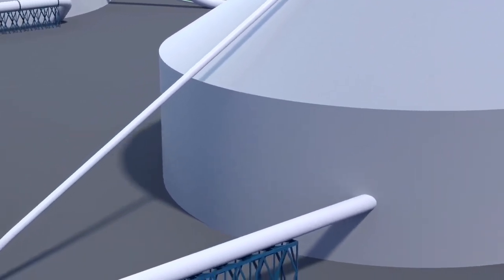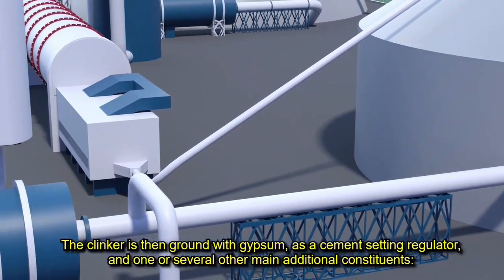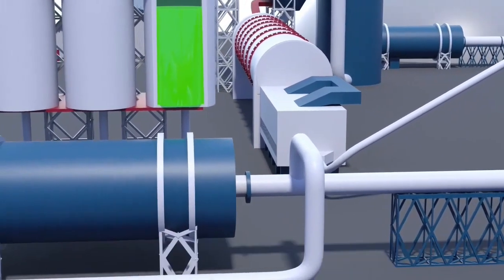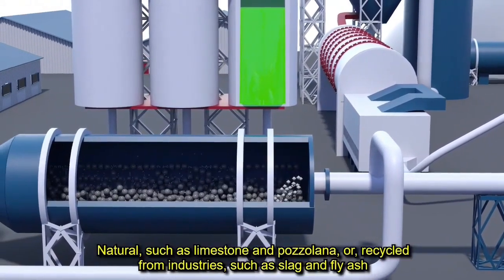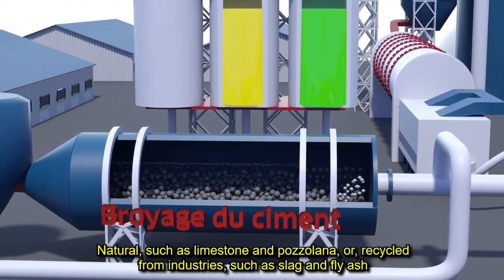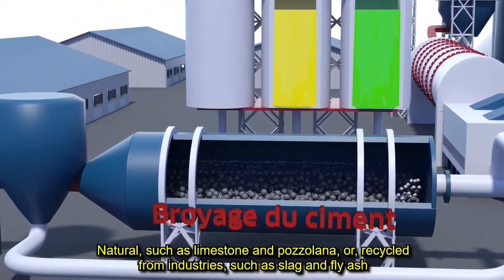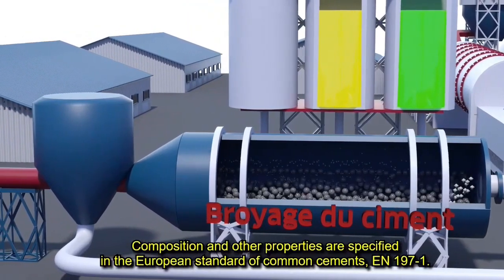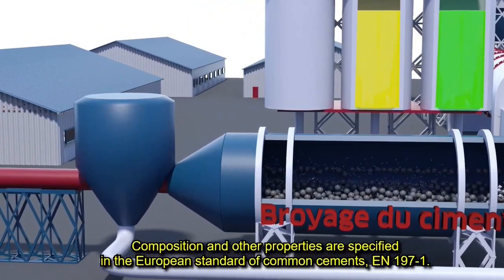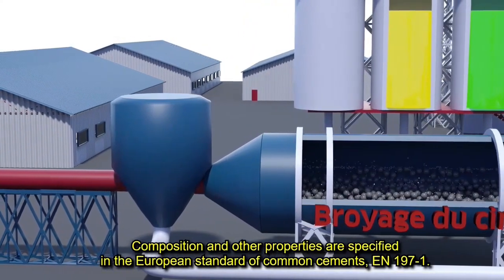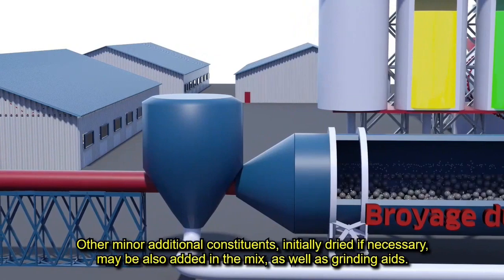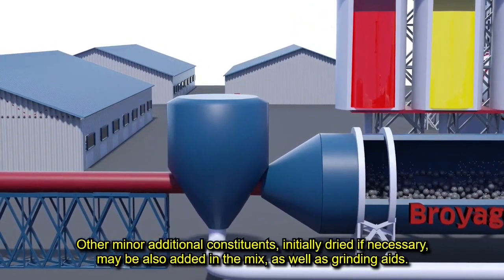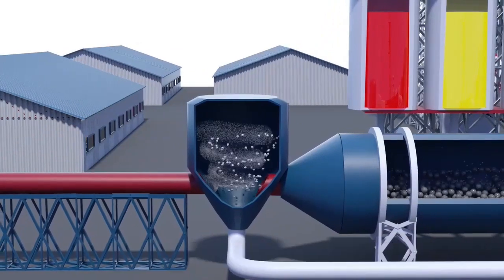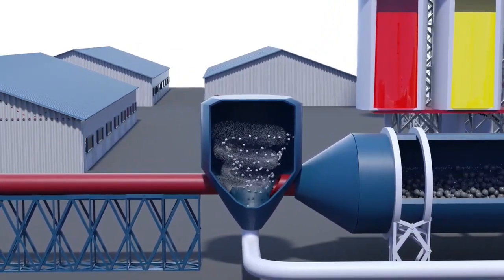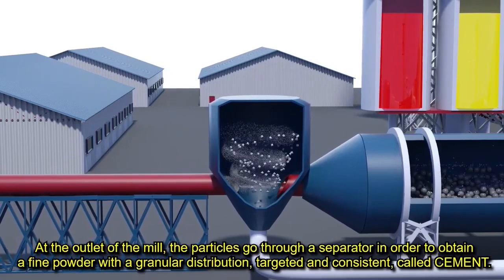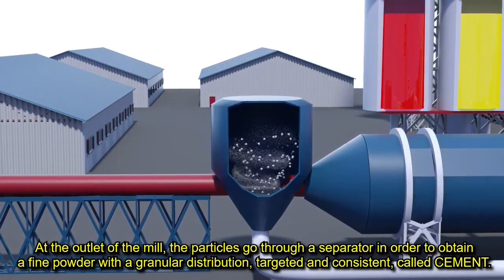Cement grinding. The clinker is then ground with gypsum as a cement setting regulator and one or several other main additional constituents, natural, such as limestone and pozzolana, or recycled from industries such as slag and fly ash. Composition and other properties are specified in the European Standard of Common Cement EN 197-1. Other minor additional constituents may be added to the mix as well as grinding aids. At the outlet of the mill, the particles go through a separator in order to obtain a fine powder with a granular distribution targeted and consistent, called cement.